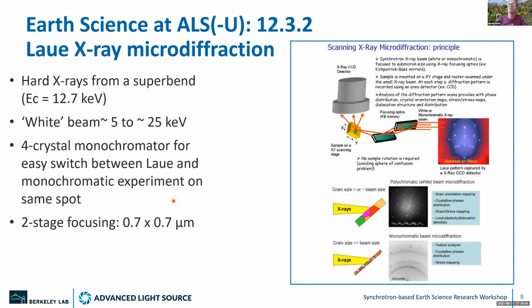If this condition is not or only partially fulfilled, the beamline has the opportunity to rotate in a 4-crystal silicon 111 monochromator. The advantage of this 4-crystal monochromator is that it leaves the beam position at the exact same spot where the white beam was before. It can then combine polychromatic white beam Laue diffraction with traditional monochromatic reflection powder diffraction experiments.